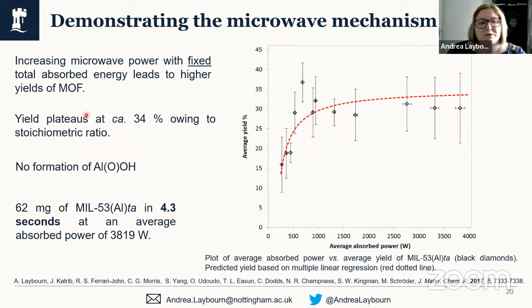We can overcome issues with penetration depth by moving into continuous flow methods, which I'll talk on in the latter part of my talk. We were also able to show that we didn't produce any aluminium oxyhydroxide, which is a byproduct which can sometimes form. This is a very unreactive, dense material, non-porous, and is quite difficult to separate from the products of reaction. And so we were very grateful that that didn't occur.